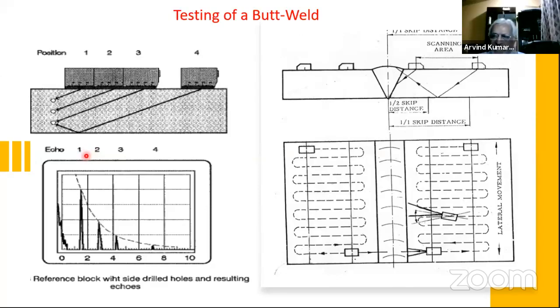But before that, you will realize that I am doing calibration on this job, which is a machined plate having machined holes, and the surface is really very good. Whereas when I do testing on the actual job, my surface may not be as good as this. The surface will be rough and sometimes rusted, and will not transmit as well as I get transmission here. So there is a correction factor, which we call transfer correction. When I transfer the probe from this surface to that surface, the difference in amplitude I get is called transfer correction. I have to note that and add it after plotting this DAC, whatever 2 dB or 3 dB I'm getting extra, to take care of the difference in the surfaces. This is a smooth surface, this is a rough surface.